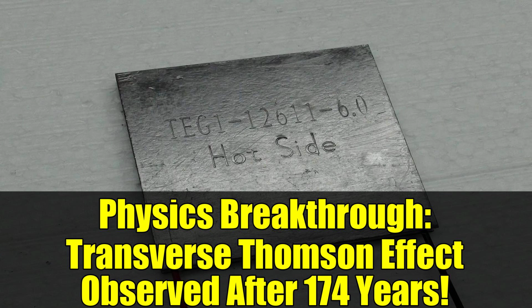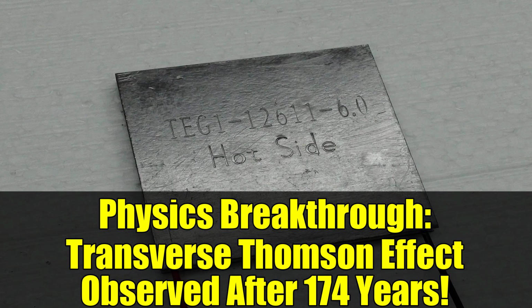Once they identified that the spatial distribution of the transverse Thomson effect differed from other competing effects, they conducted measurements both with and without a temperature gradient. By subtracting these results, they were able to isolate the pure transverse Thomson signal.